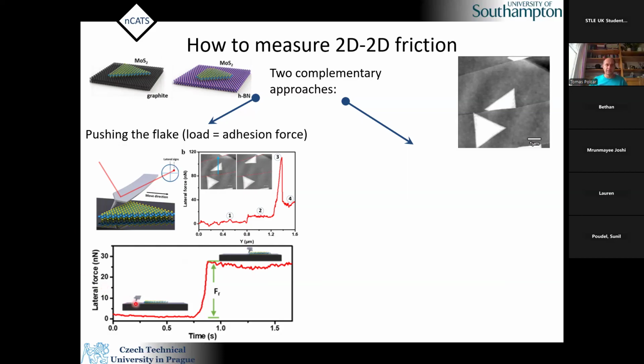You slide your AFM tip over the surface from left to right, and there is this low friction here. And when we hit the flake, of course, you need to increase the force, which is this difference, to start to move the flake. And this difference is exactly the friction force induced by sliding of this small flake. So we were able, as the first in the world, I think, to measure genuine 2D to 2D friction without any other influence.